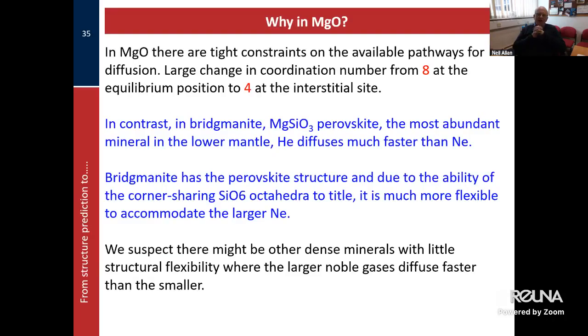Whereas having the helium, a better model would be having a cat in the china shop. Not entirely happy, but there is then more of an activation energy. It's happier in some positions rather than others. A key thing is that because of the simple structure, there is a large change in its coordination number from 8 at the equilibrium position to 4 at the interstitial, the transition state for the migration, and that turns out to be important.